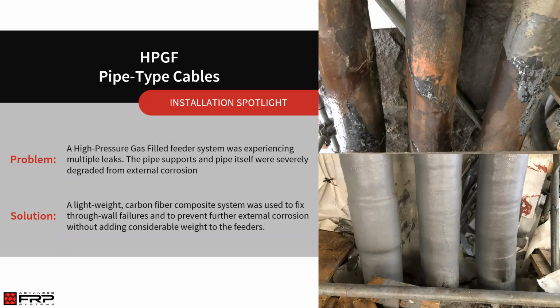We also ran into some unique issues with high pressure gas filled pipe type cable systems. Certain utilities at bridge crossings switch from dielectric fluid to nitrogen gas. On these feeders, they were a gas filled feeder system, and there were numerous leaks on this particular feeder system we reinforced. Not only were there numerous leaks, but the pipe supports themselves were aging in pretty bad shape. So the amount of weight that we added to these feeders was critical.